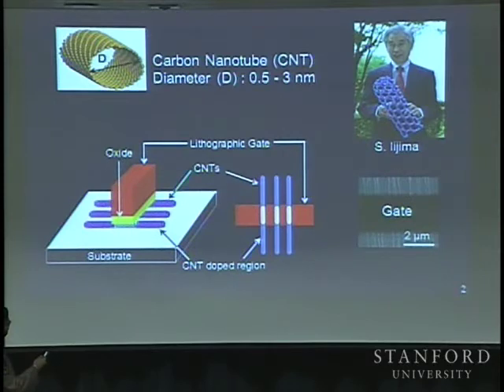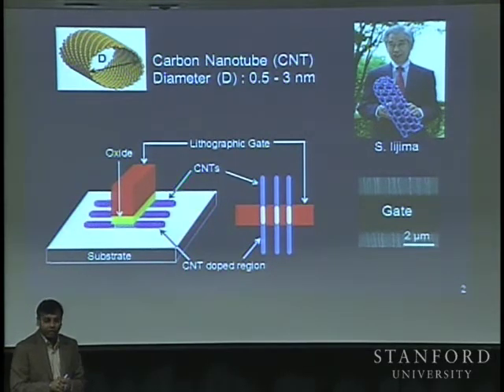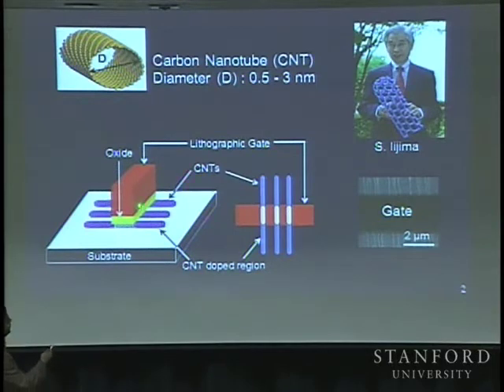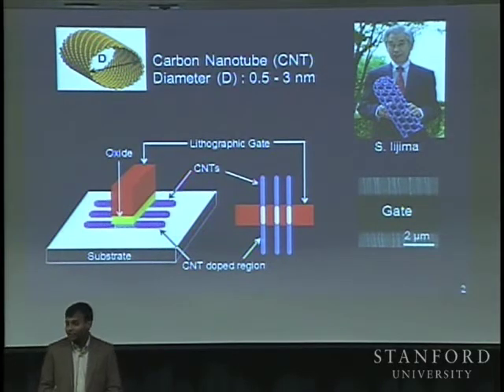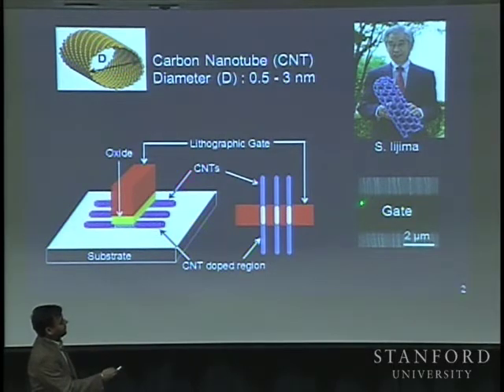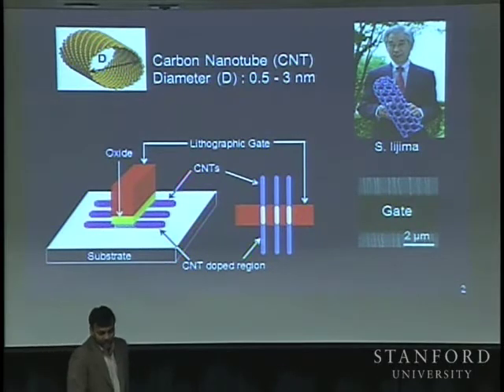Look at the part of the carbon nanotube under the gate. That part is supposedly undoped, because that's like an intrinsic material. And if these carbon nanotubes are semiconducting carbon nanotubes, that means that they will have some sort of a band gap, which means that depending on the voltage on this gate, you will be able to control whether there will be current flowing through this carbon nanotube or not. That would make a transistor. And are these transistors real? Yes, here is an SEM image. You can see these carbon nanotubes and you can see the gate. So we made a transistor.